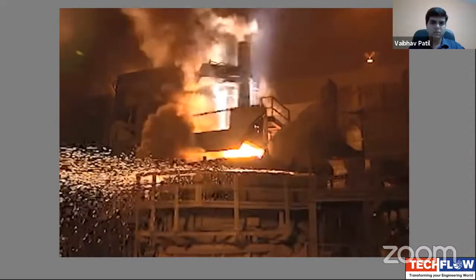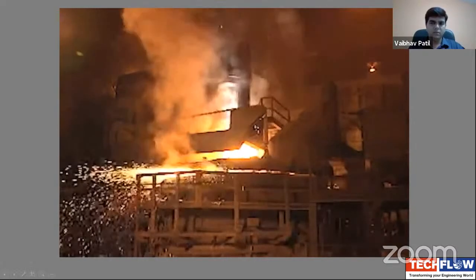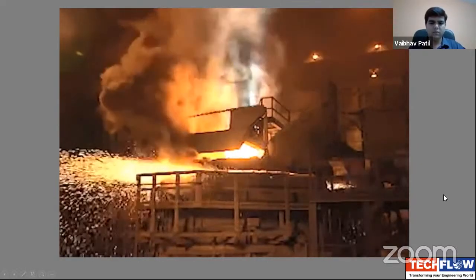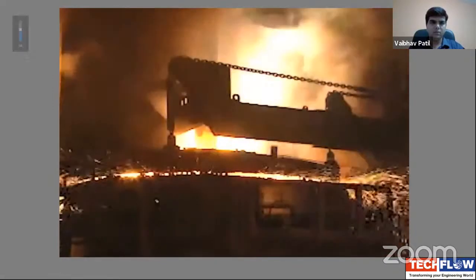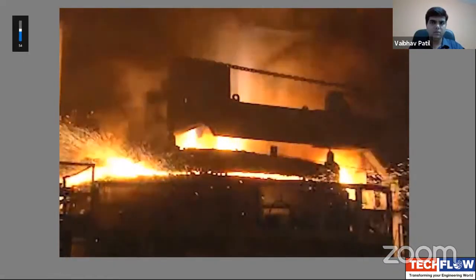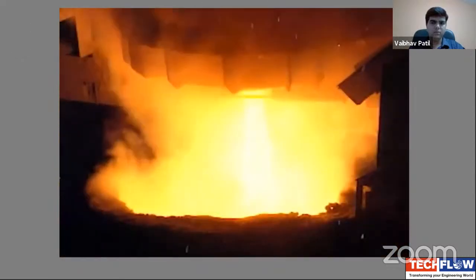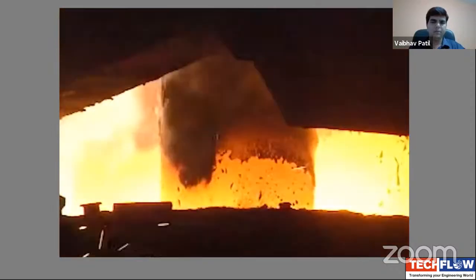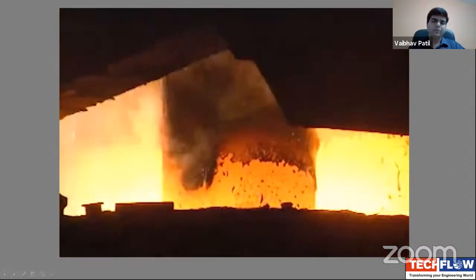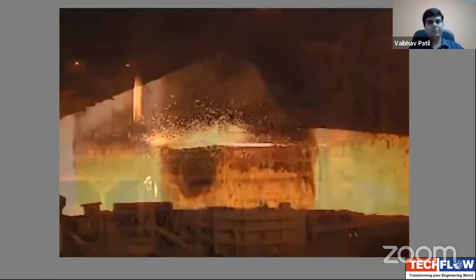This electric arc furnace, consuming about 75 megawatts of electricity, just melted about 125 tons of used cars and other forms of ferrous steel scrap in about 60 minutes. The electricity arcs between the carbon electrodes and the steel scrap in the furnace to produce a heat of molten steel.